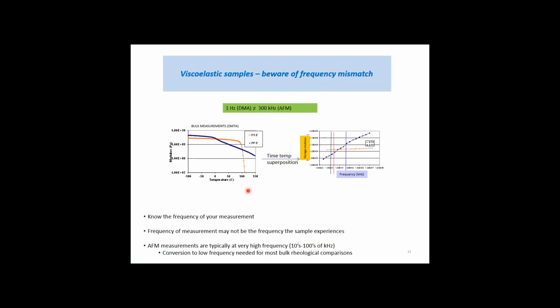Now for viscoelastic samples, another word of warning is you have to be very careful of the frequency mismatch problem. What this refers to is that AFM is fundamentally done at high frequencies. So the cantilevers are resonating at tens or hundreds of kilohertz if you're using a resonant-based method. Even if you're using force curves, those are typically done at a rate of 1 or a couple of kilohertz. Those are high frequencies compared to where our bulk measurements are made, like by a DMA, for example, which are typically done at very low frequencies of 1 hertz to a maximum DMA can handle is maybe 200 hertz. So that's several orders of magnitude difference in terms of frequency space that's being sampled by these two measurements.